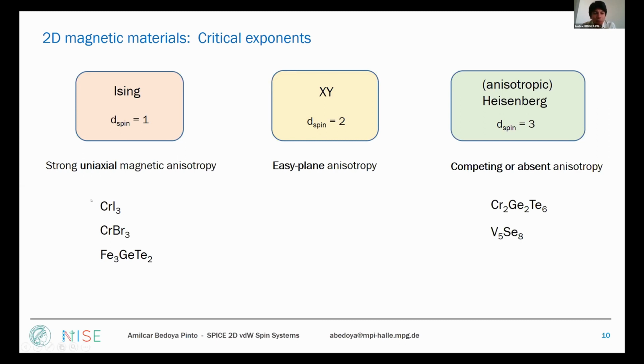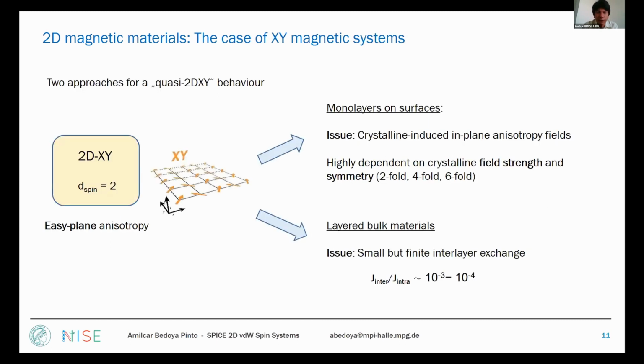There's another important thing here: many theoretical works say that both chromium iodide and chromium bromide are not fully Ising systems. That means you will probably have other types of interactions that compete with this uniaxial out-of-plane anisotropy. This is just to give you the information that this is a broad classification, but inside all these types of magnetic models, there are also very fine details.